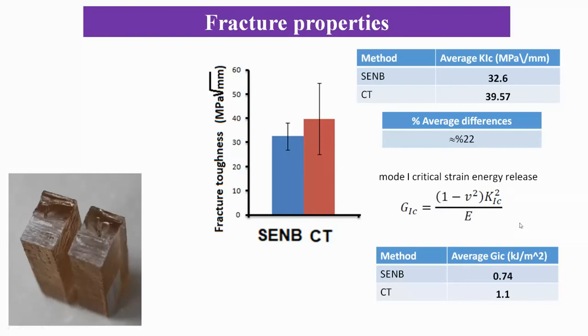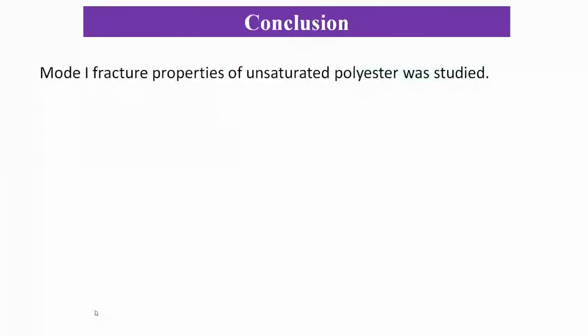Mode 1 strain energy release rate can be obtained through the formula shown in this slide, which results in values of 0.74 for SENB and 1.1 for the CT specimen. On the left side, you see the fracture morphology of a SENB specimen.